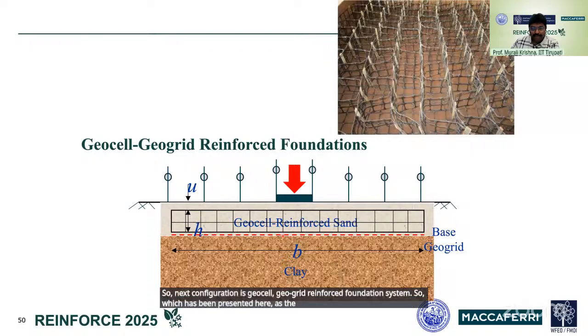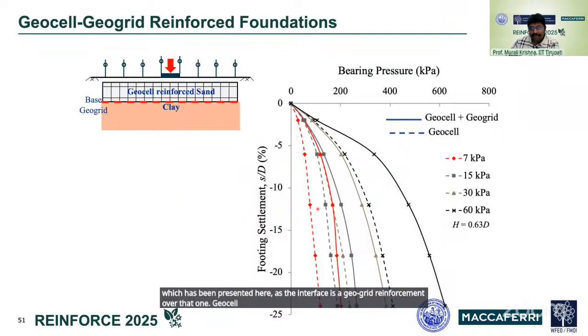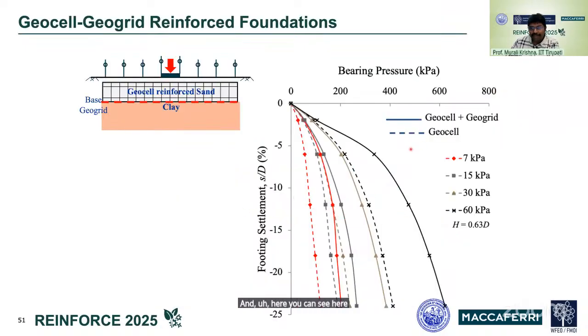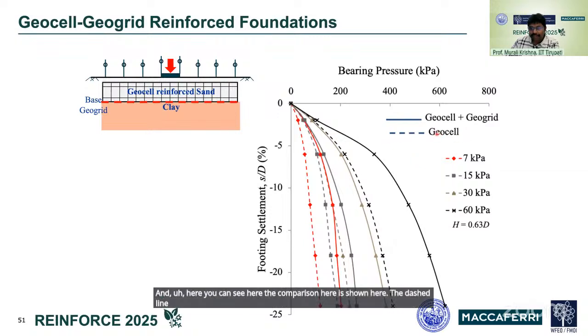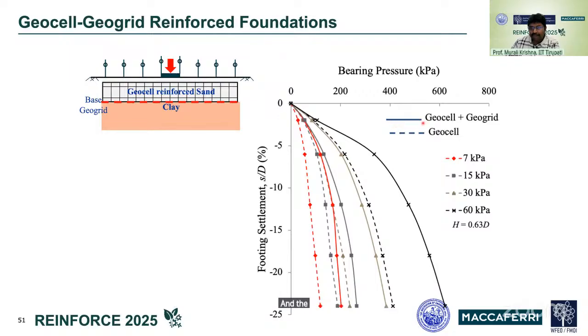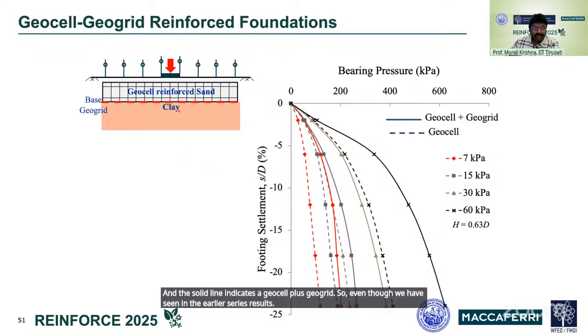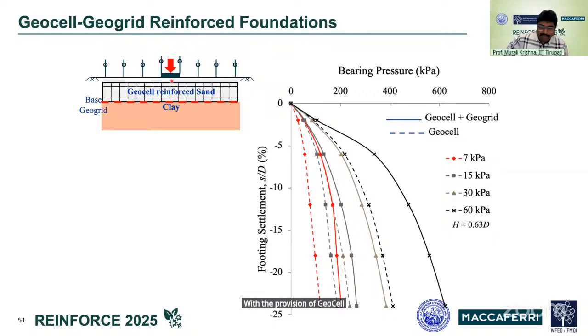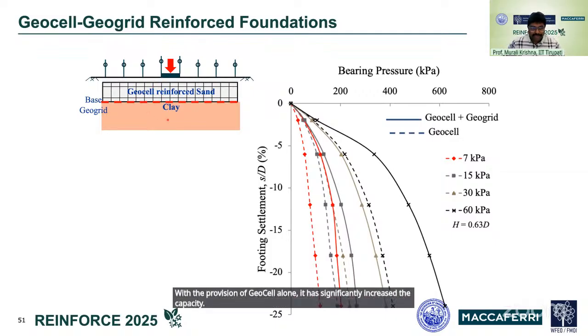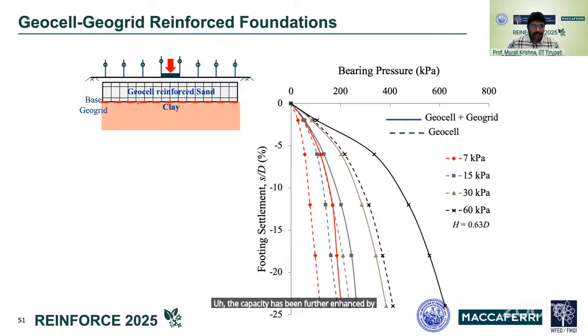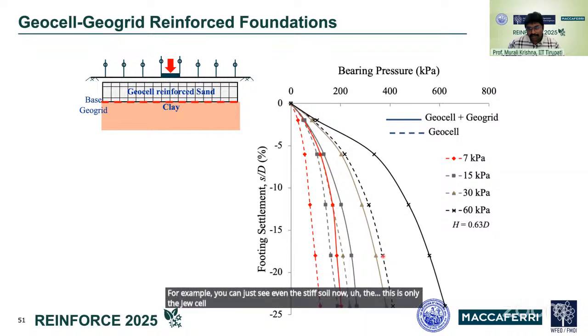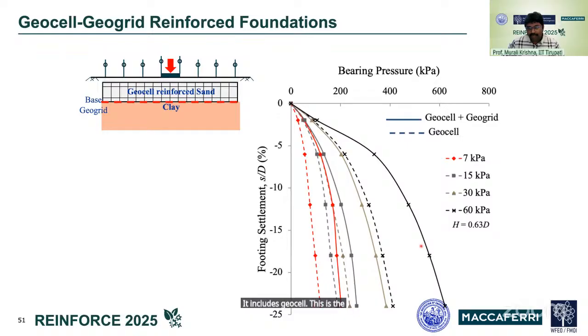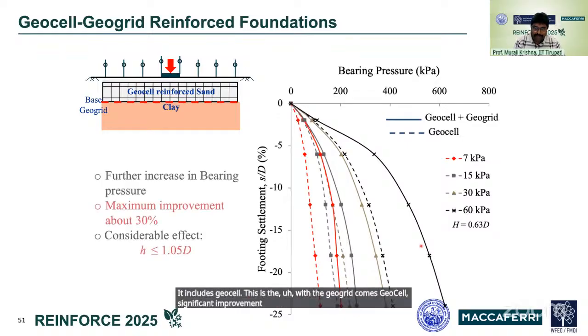The interface has geogrid reinforcement, and over that the geocell has been placed. Here you can see the comparison. The dashed line indicates only the geocell and the solid line indicates the geocell plus geogrid. Even though we have seen in the earlier results that the provision of geocell alone significantly increased the capacity, the capacity has been further enhanced by inclusion of the base geogrid. For example, you can see even the stiff soil now. This is only the geocell, and this is the geogrid with geocell, and a significant improvement has been shown here.